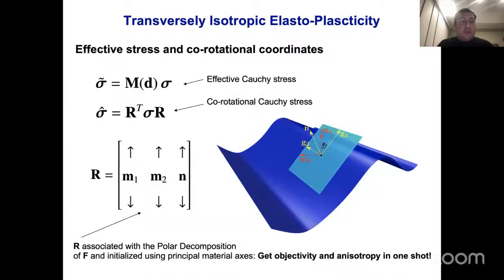So again, let me take us through some of the modeling details, some of which are fairly traditional and some of which are new. First, to model plasticity, we work with the effective Cauchy stress in the corotational system. The corotational system involves the use of a rotation matrix here. The rotation matrix is associated with a polar decomposition of the deformation gradient, which means that it will rotate with the material axis. And the key is that it's initialized using principal material axis. So at every integration point, or at every material point, wherever I need the stress, the rotation matrix is initialized pointing in the direction of fiber and matrix and through thickness direction, like this. And then it's advanced in time using an appropriate algorithm. So with this technique, you get incremental objectivity for large deformations and anisotropy at the same time.